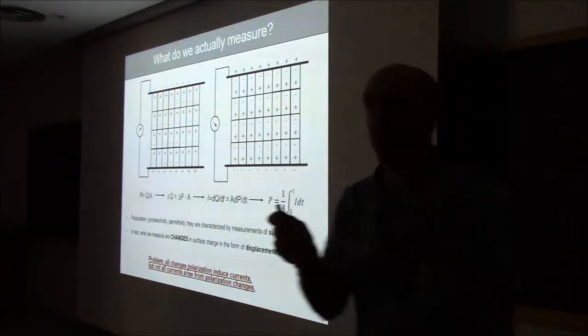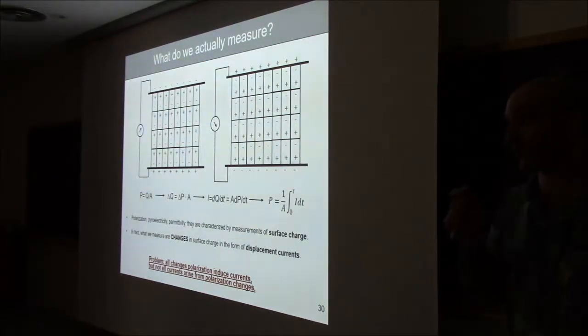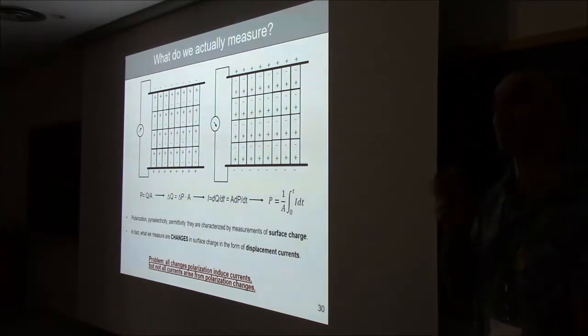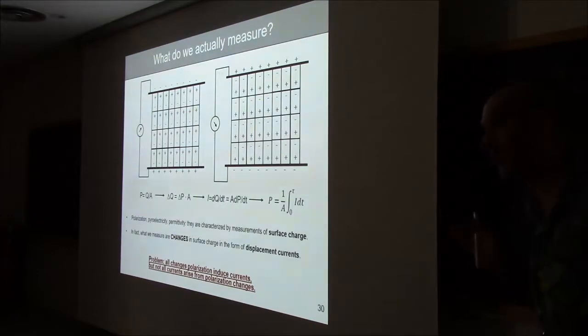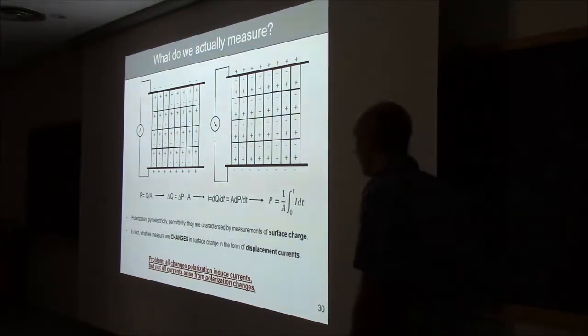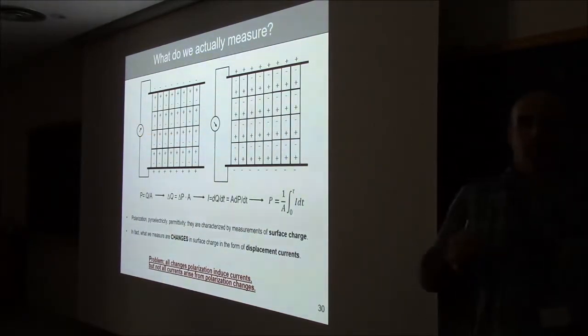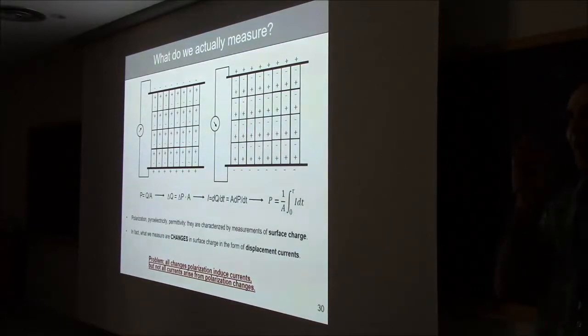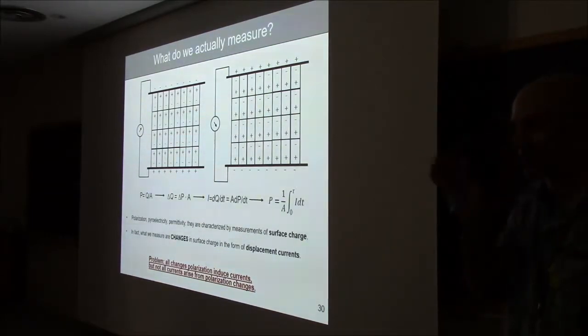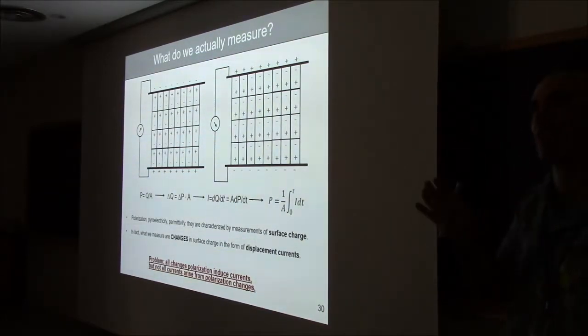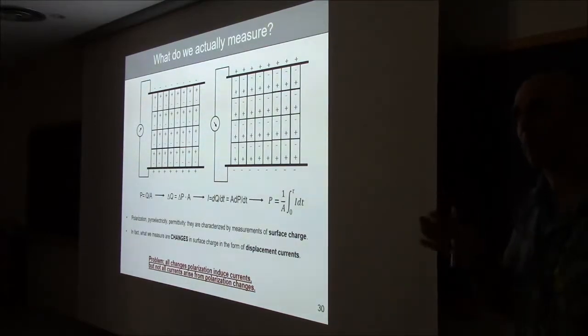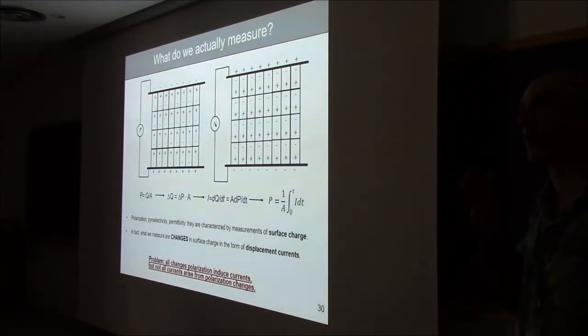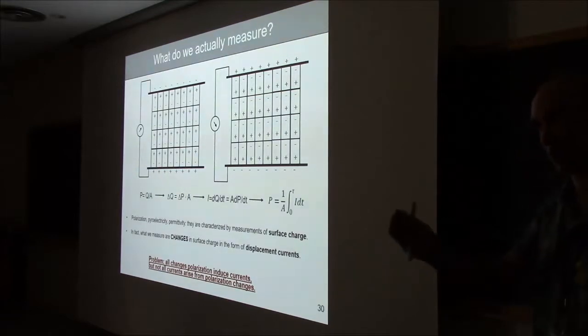This is to say, I am not measuring polarization. I am not even measuring charge. I am measuring changes in polarization, and that's very important. I believe it's almost a universal truth that polarization per se is not a measurable quantity. You can only ever hope to measure changes in polarization.